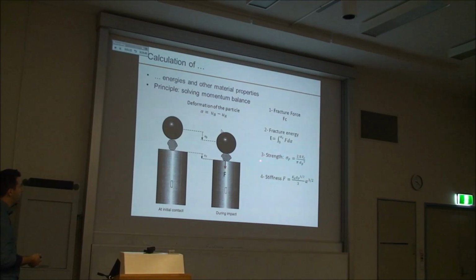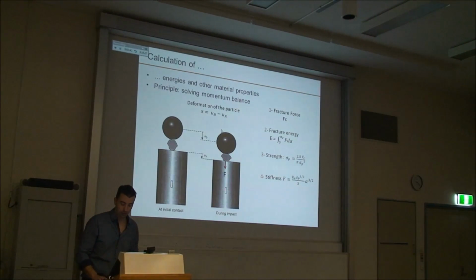Another property that can be derived is the strength. This is assuming a spherical particle. And using the fracture force, the strength, which is in megapascal, can be estimated. And the stiffness of the particle, the stiffness is like the elastic properties. The elastic properties are related to the stiffness of the tools, which is the stiffness of the steel bar and the stiffness of the ball. By doing a ratio of the stiffness observed and the maximum compression at fracture, then you can estimate the stiffness of the particle. So this is quite a lot of information just by doing one impact.